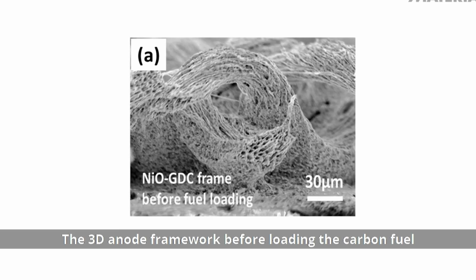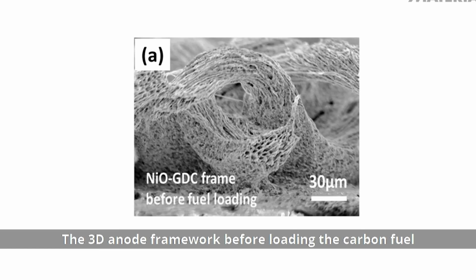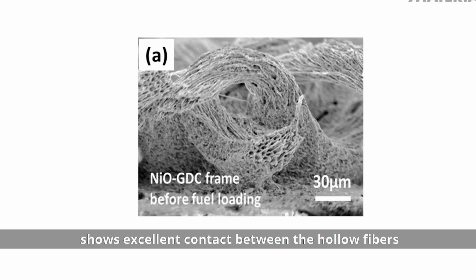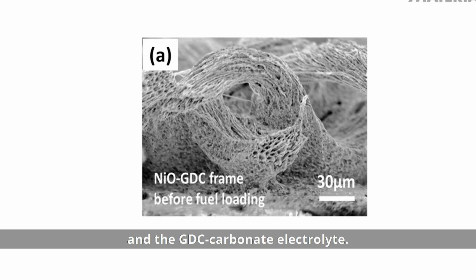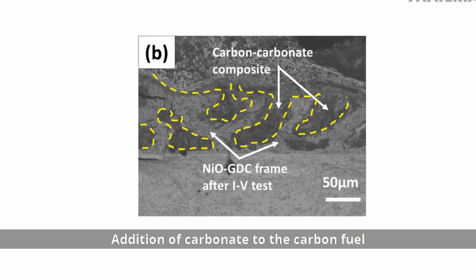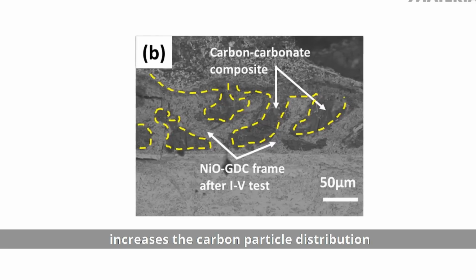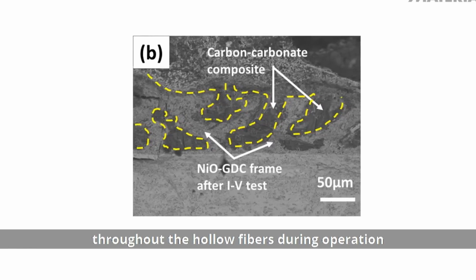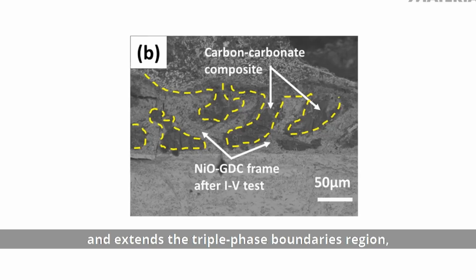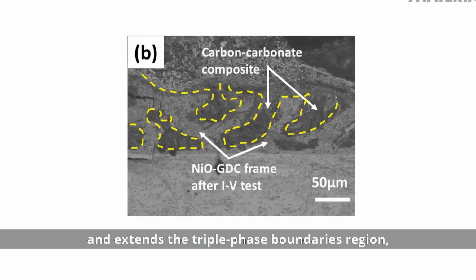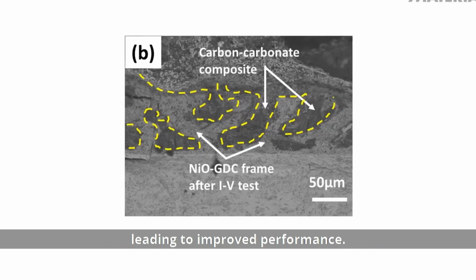The 3D anode framework before loading the carbon fuel shows excellent contact between the hollow fibers and the GDC carbonate electrolyte. Addition of carbonate to the carbon fuel increases the carbon particle distribution throughout the hollow fibers during operation and extends the triple phase boundaries region, leading to improved performance.